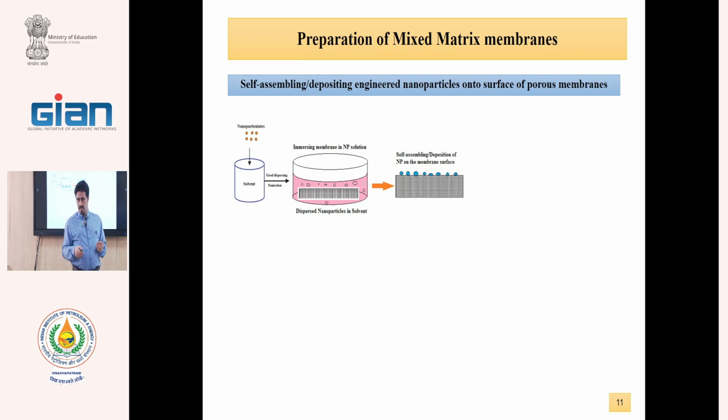But nanoparticles are not stable because they are physically attached, and when we use the membranes with cross-flow fluids, this cross-flow tension can separate the nanoparticles, and after 1 day, we have no nanoparticles. Therefore, this is efficient because they are located on the membrane surface, but the attachment is problematic.